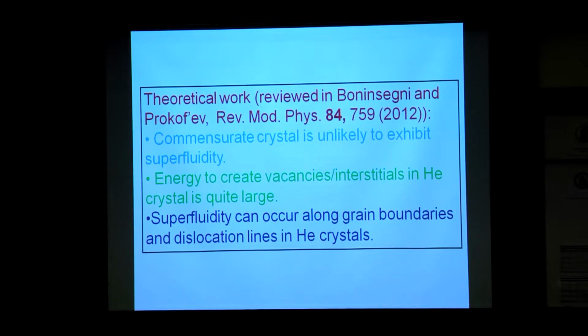But several other people also showed that in this helium, one can actually get superfluidity, not when the crystal is a perfect crystal, but every crystal typically will have some defects, and the defects could be dislocations, grain boundaries, and so on. And there is evidence from quantum Monte Carlo simulations saying that along grain boundaries and dislocation lines in helium-4, there could be superfluidity. So this is an alternative mechanism for supersolid behavior, in the sense that you have a solid